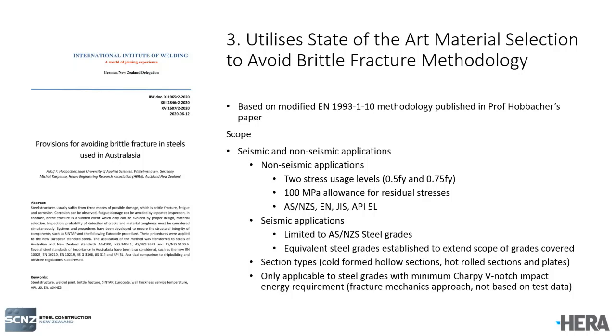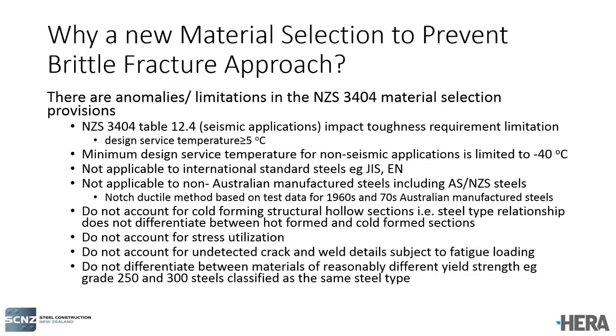Selection also includes cold forming, so the hollow sections are included, but we also consider the effect of cold forming or strain hardening in the corners or in the base material of the hollow sections. We base those requirements on the known impact toughness properties of the steel from the product standards, so they are not applicable to steels without defined notch toughness. Next slide, Alistair.